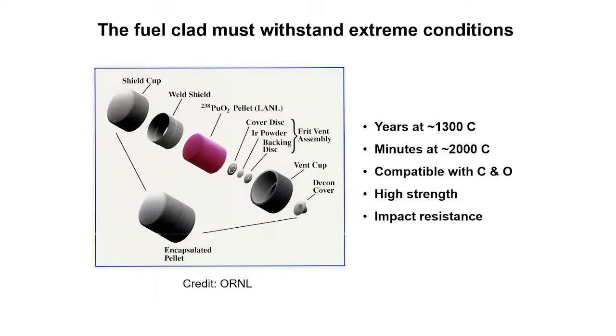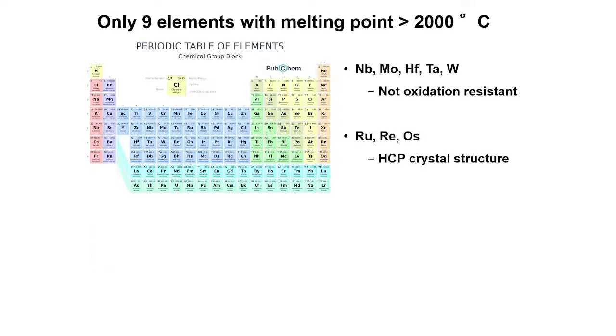So if you know your Ellingham diagrams, you know that in thermodynamics, there are very few materials that are compatible with both carbon and oxygen at 1300 C for years at a time, right? And then it has to have high strength in case there's an accidental impact, and it has to have good impact ductility if, for whatever reason, there's an accident and it crashes into Earth. So when you look at the periodic table, right, there are just a handful of elements that have melting points greater than 2000 C. So you're kind of limited. Nature limits you in what you can use.